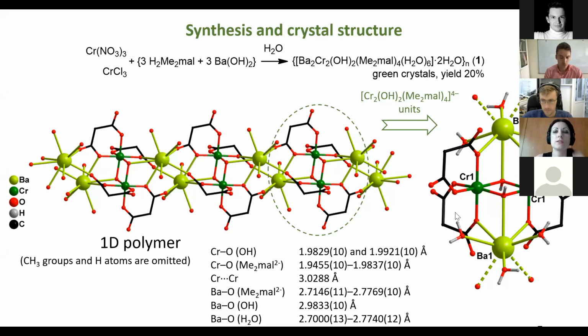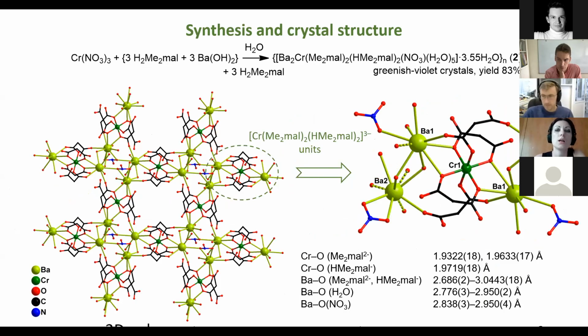In the crystal structure, these binuclear units are linked to each other through barium atoms, which are coordinated to carboxylate oxygen atoms and hydroxyl groups to form polymeric chains. Each barium atom is additionally coordinated by free water molecules. The use of chromium chloride instead of nitrate in the similar reaction had no effect on the structure of the reaction product.